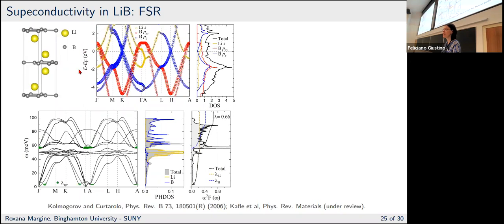And you also have something like in graphite intercalation compounds, which are these lithium states that have this parabolic band. These are nearly free electron states, and this is the main driving interaction in, for instance, calcium C6. So it seemed that this material basically had both key ingredients that would make it a high TC superconductor: the key ingredient from MgB2, hole-doped sigma states, and NFE states.